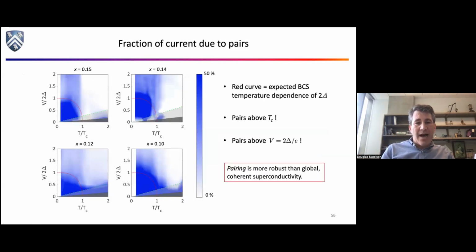So that's why in these plots here, I've done a color map of that Z number. And the color scale ranges from 0.5 to 0. And these shaded regions are where you really shouldn't trust that Z number very much because the voltage scale is small. But what you find is that the red curve is what you should see for a conventional superconductor. That's the boundary of the superconductivity, basically. And what you find is there's a lot of blue outside that boundary. There's a lot of indication of pairing outside that boundary at high temperatures, right? And also at voltages that are big.